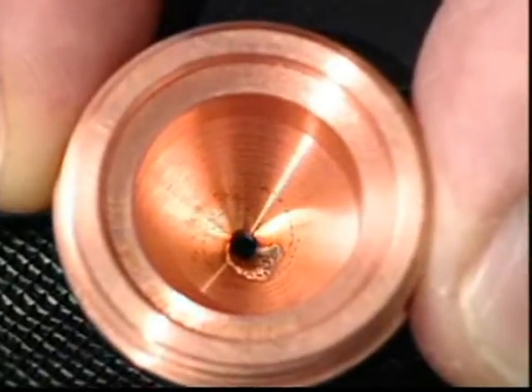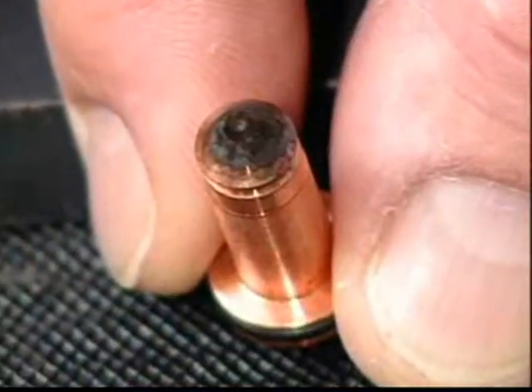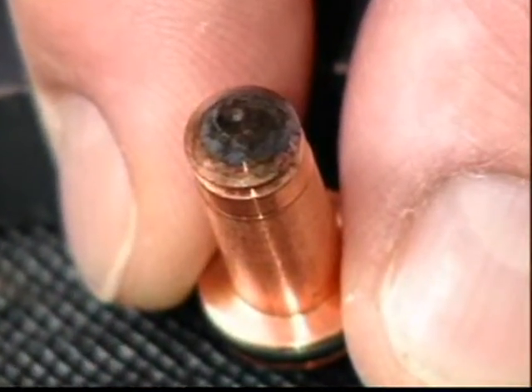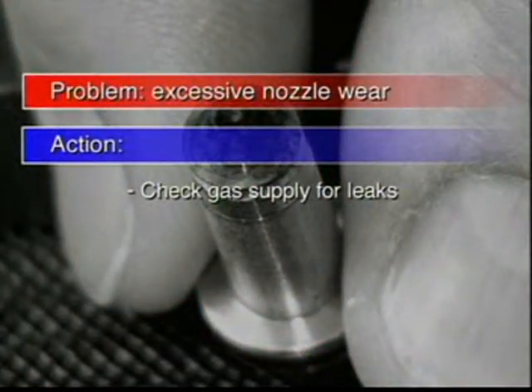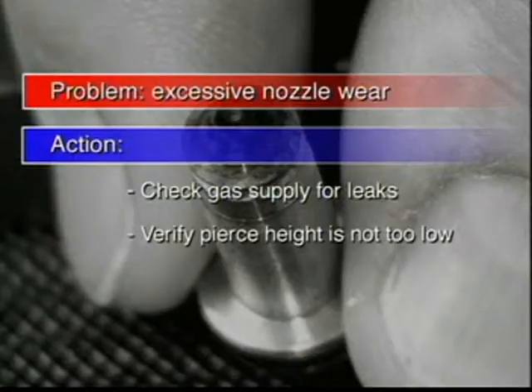If the nozzle erodes on the inside or the electrode tip blackens, the cause may be gas contamination, and you should check the gas supply for leaks. Double arcing may also be a cause, and so pierce height should be checked to make sure it isn't too low.